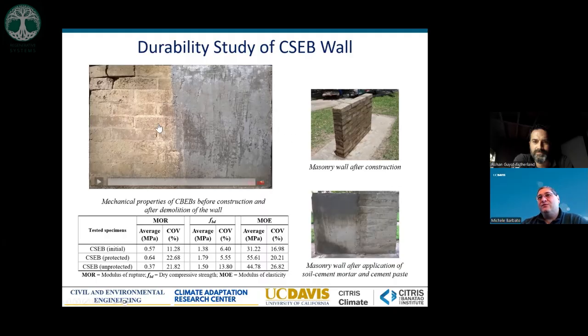However, we looked at what happened to this wall. After the 6 months, we demolished the wall by taking it apart brick by brick, and then we tested the components again. And so what we found is that while the unprotected side had a degradation of the strength, the protected side, which even visually looks perfect just by looking at it, not only didn't have any visual damage, but actually the properties kept increasing. The strength, both modulus of rupture and dry compressive strength, were significantly higher than the original material. And that is because the amount of humidity that was provided by the water kept the cement reacting with the soil, and so that's why the material became stronger and stronger when we retested it.